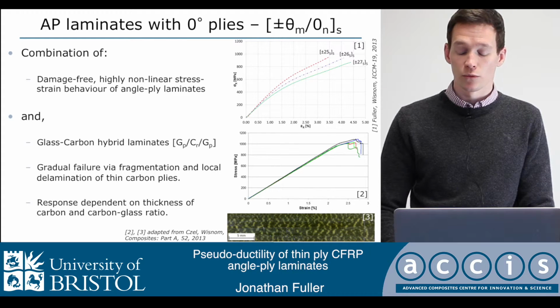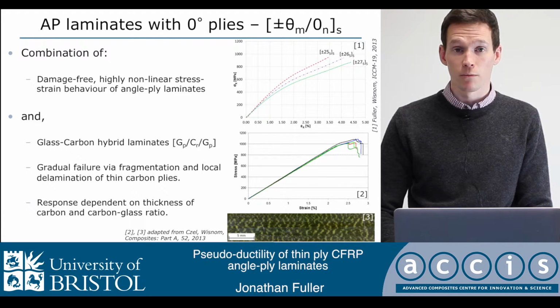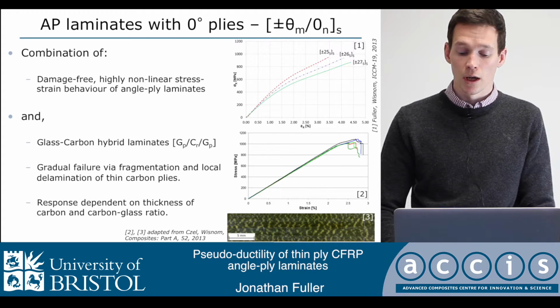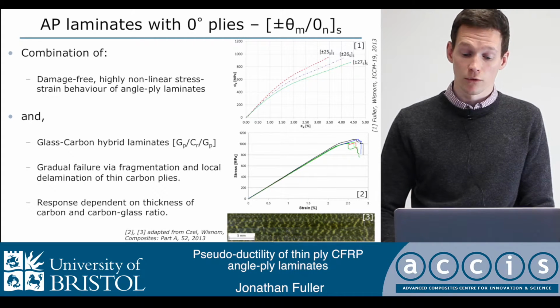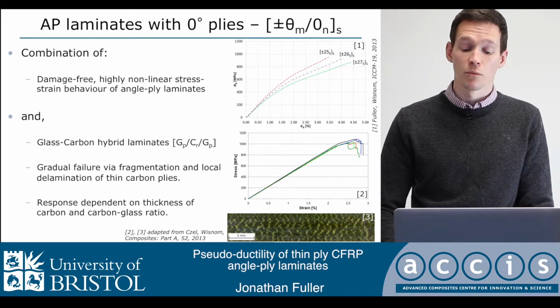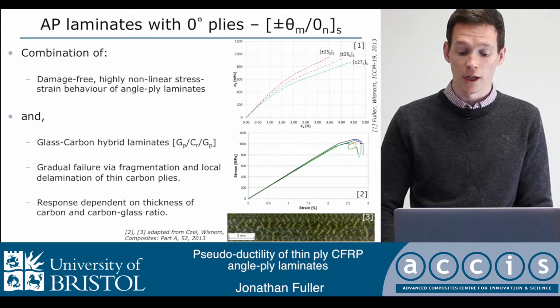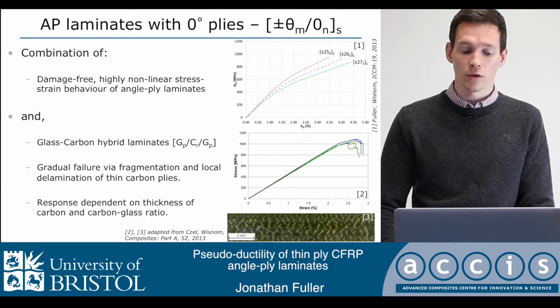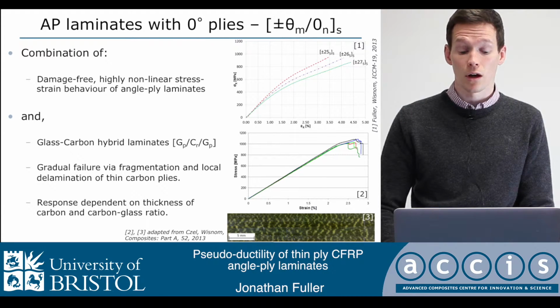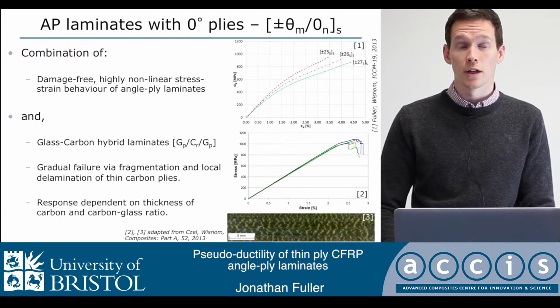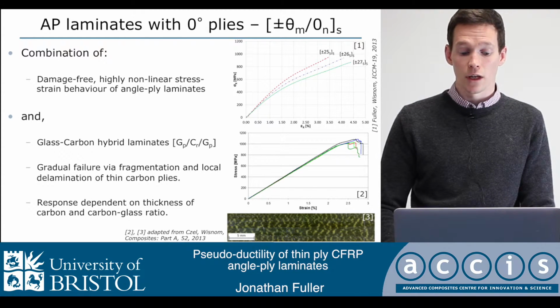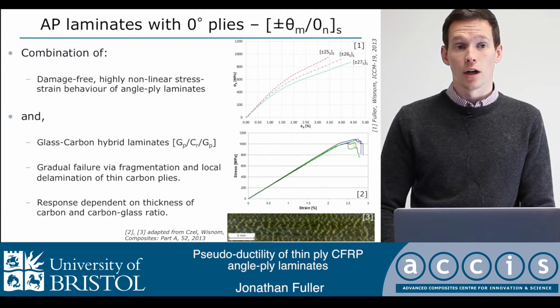The nonlinear stress strain curve that Czel managed to produce is shown on the right and the lower stress strain curve, and then the picture at the bottom shows the sort of tiger stripe pattern, as we're calling it, which indicates that the carbon layers are fragmenting and then delaminating locally to around the fractures of the carbon, but not propagating and not joining up, which is a key point which creates this tiger pattern.